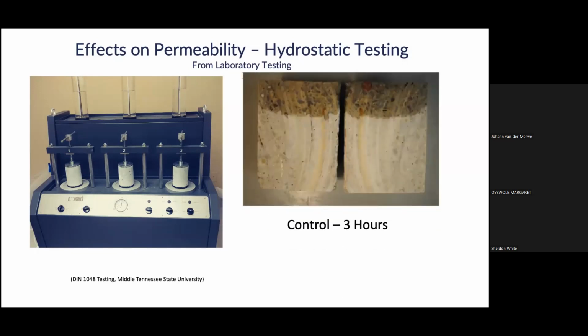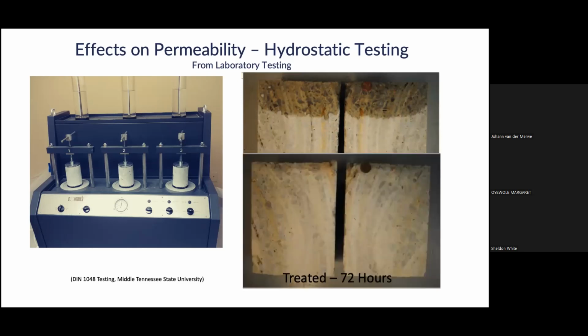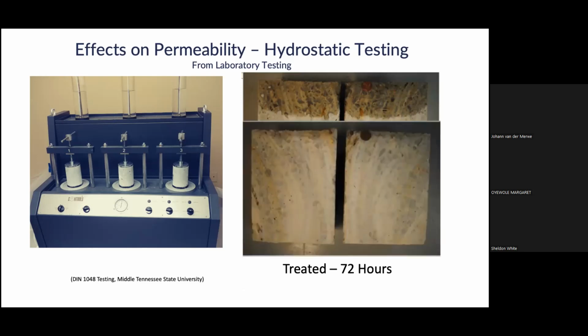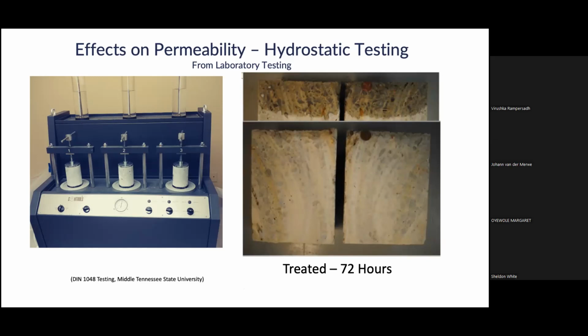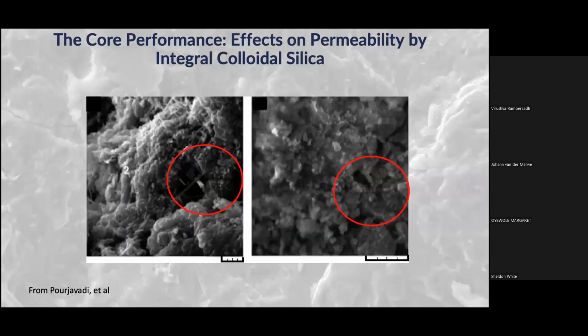The control specimens actually failed at 3 hours. This is a 72-hour test. At 3 hours, water was coming out of the sides of the samples, which the test method will tell you is a failure of the test. You stop the test. The treated samples at 72 hours demonstrated very little penetration into the concrete, I think we called that 5 millimeters of penetration. So we typically see with colloidal silica a reduction in hydrostatic permeability somewhere in the 90 to 100% range, depending on the concrete. So integral colloidal silica can close capillary void structure, and it does a decent job at it.